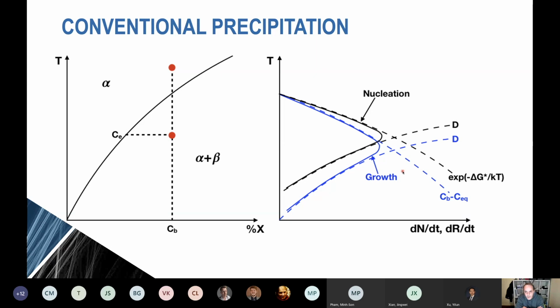Actually, what we would like to do is maximise the nucleation and have very little growth to get this really nice, fine and uniform distribution of particles. But to maximise nucleation in a thermodynamic sense, we want to go to low temperature. But at low temperature, we don't have enough mobility. And so we make a compromise.